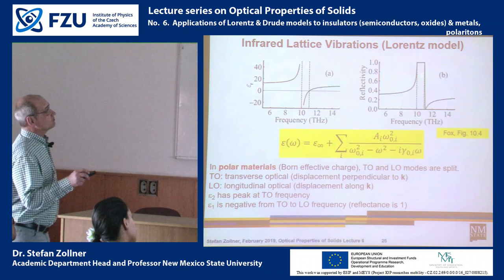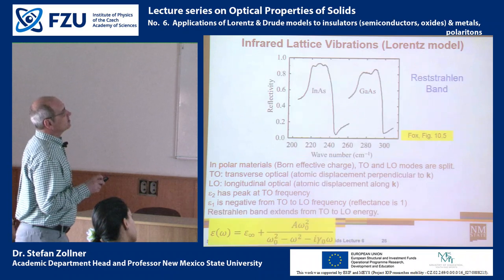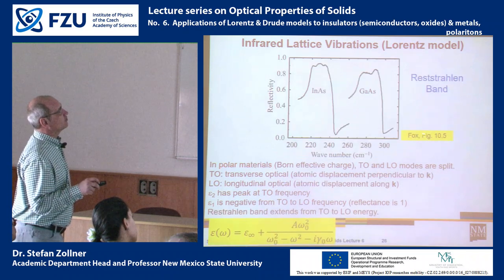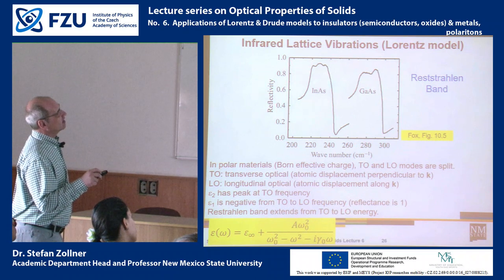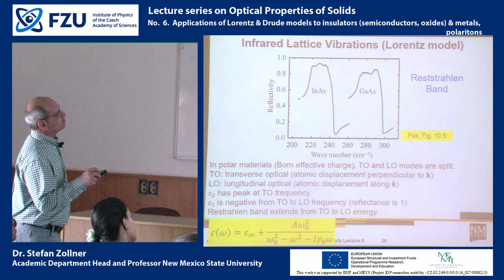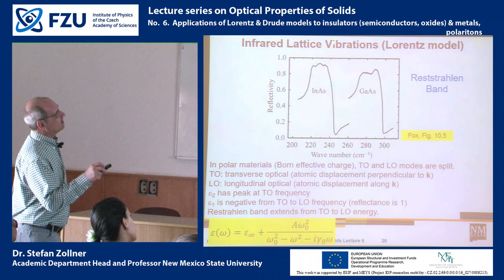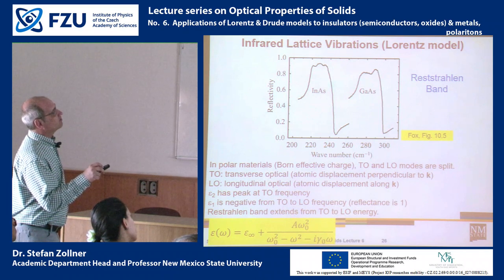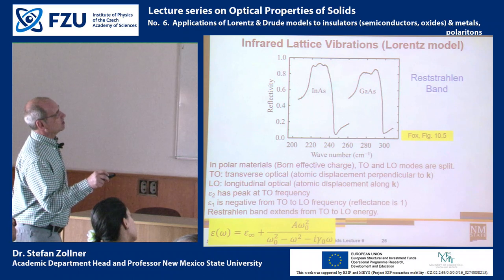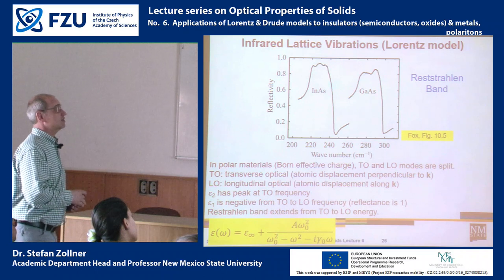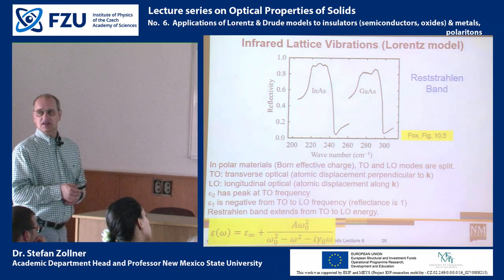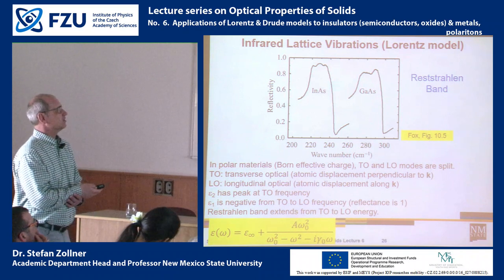So that was the theory. We should have this band. And here are actual examples taken from FOX. So this is indium arsenide and gallium arsenide. And the reflectivity goes up, does not quite reach 1. And then we have this plateau, and then the reflectivity drops. So that's the TO frequency, and that's the LO frequency. And this band of high reflectivity, that is called the Reststrahlenband. And where this band is located in frequency, that, of course, depends on the reduced mass of the two atoms in the lattice.